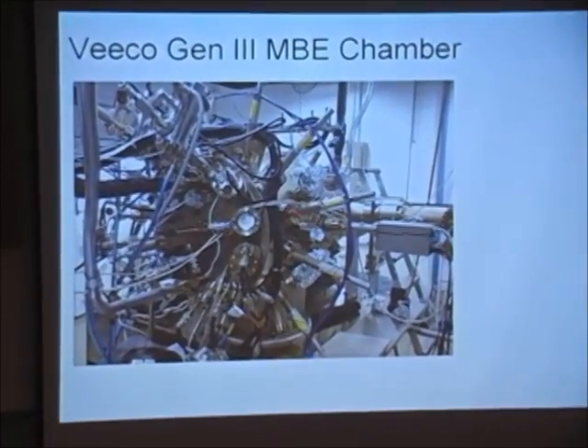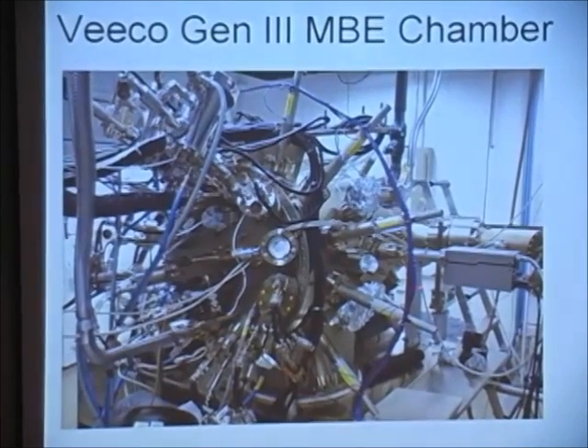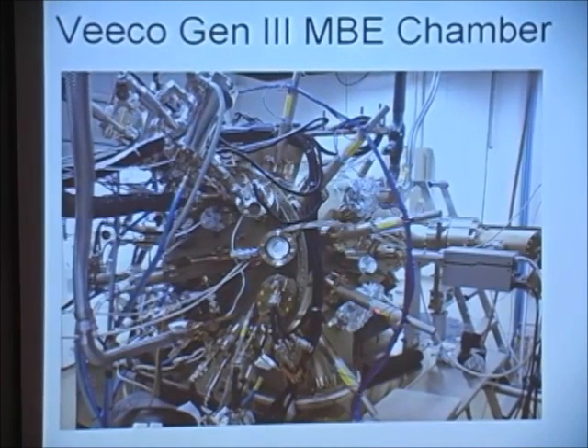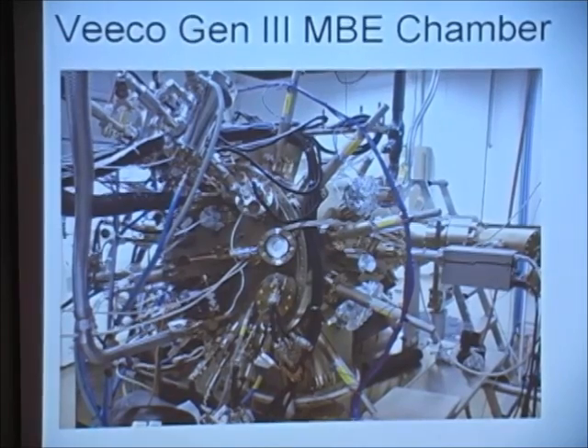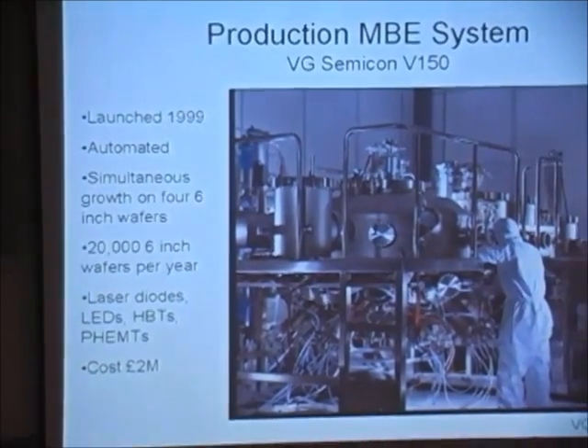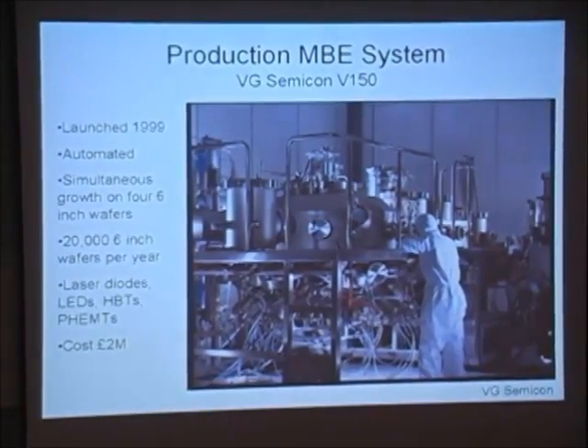I saw an MBE chamber here today, very similar to that. And you can see essentially what these sticking out are. These are actually ovens in which we put material. They're heated up to high temperatures. The vapor comes off, and within the high vacuum in there, there's a substrate on which they condense, and we can grow atomic layers at a time. That's actually a production MBE system. He's of normal height, so you get an idea of the size of the facility.